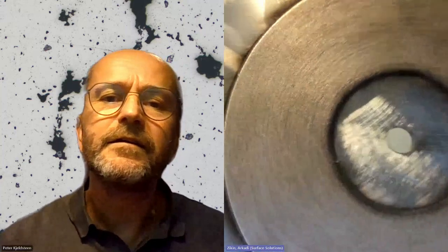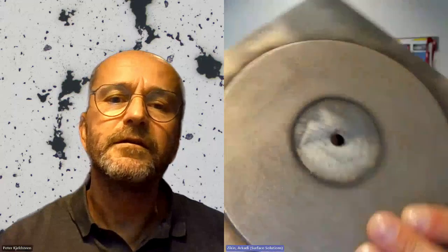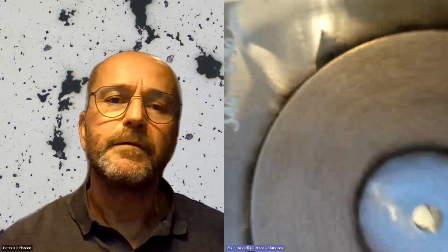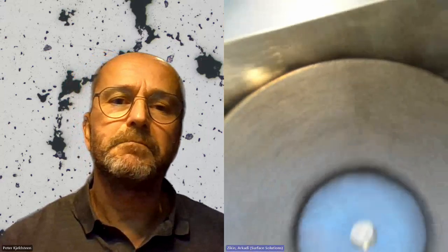Sure. Slides show something, but slides don't give you a full idea about what is happening. So with high-speed laser cladding, the typical surface after deposition looks like this. There is a roughness, but we can achieve something between Rz 20 to 50, depending on process parameters, depending on how you treat your process. So it's a pretty even surface. You, as an expert in thermal spray, would probably say it looks quite typical for thermal spray. Yeah, but it looks pretty flat compared to HVOF.